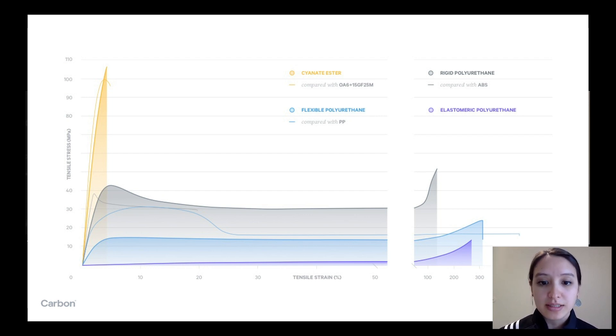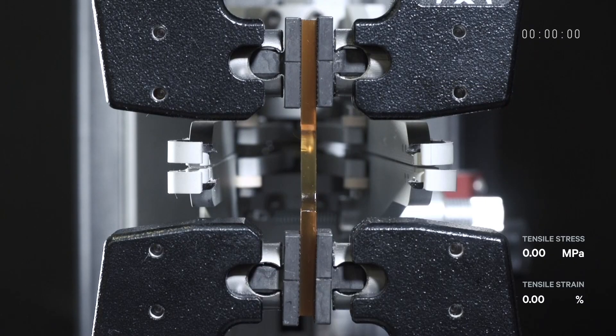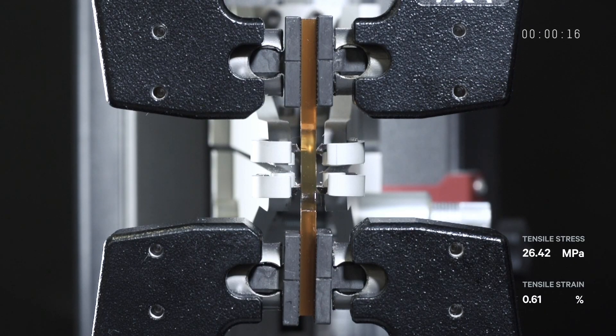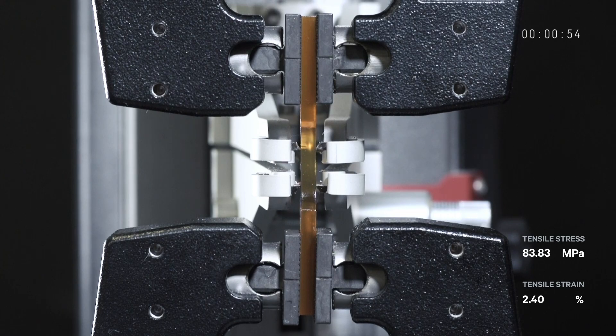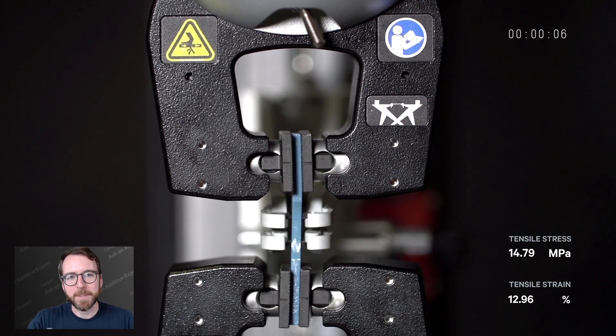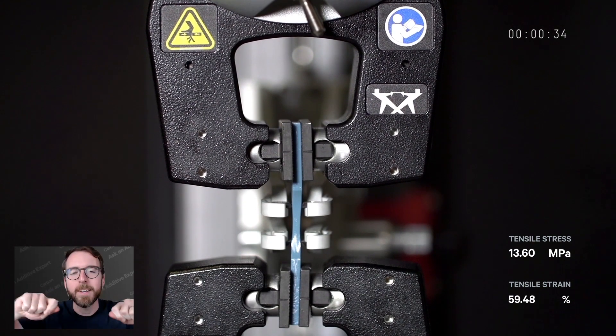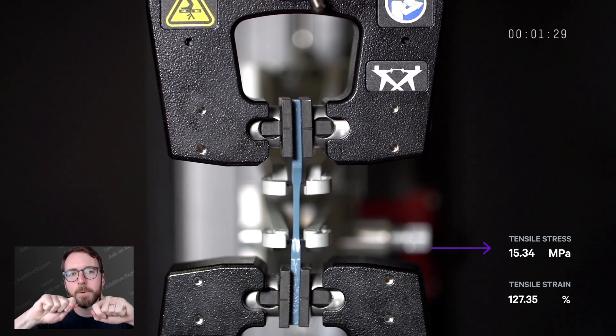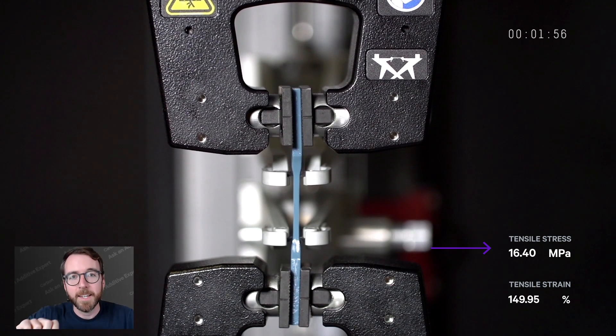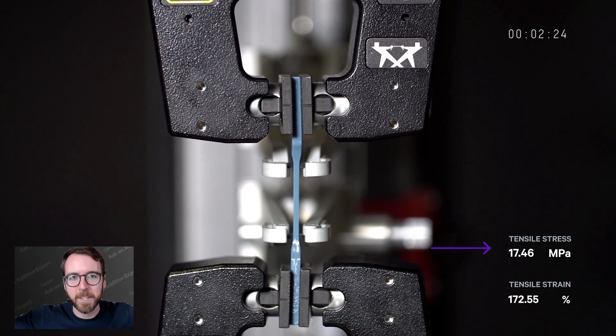At the highest end of the scale, you can see cyanate ester, which has a very sharp slope that goes up very quickly, corresponding to a really high modulus. In intuitive terms, as you go along the x-axis of the graph, the machine is pulling the material apart, and the y-axis tells you how much stress you need to apply to do that. For the elastomeric polyurethane, it doesn't take a great deal of stress to really elongate it, whereas for CE221 — that cyanate ester material — you're having to add a lot of stress. That's exactly right.